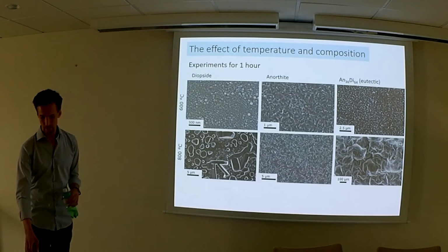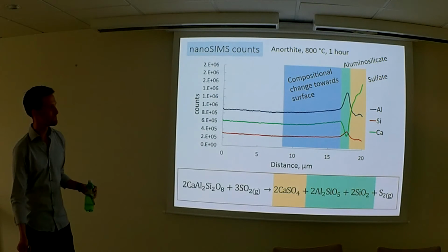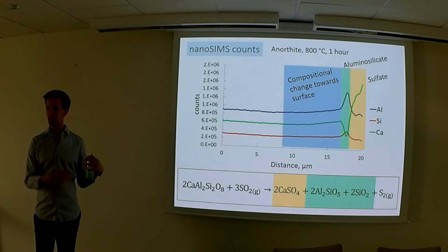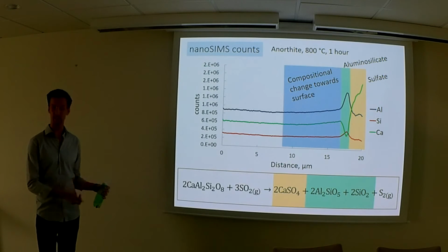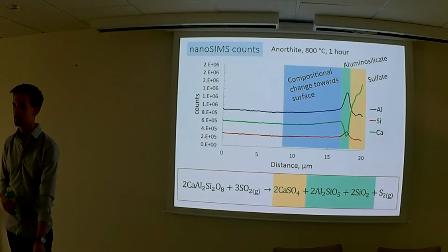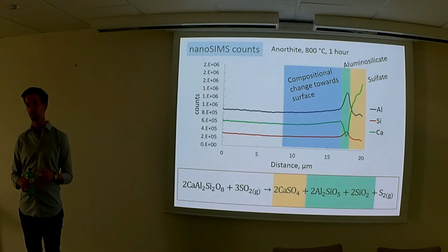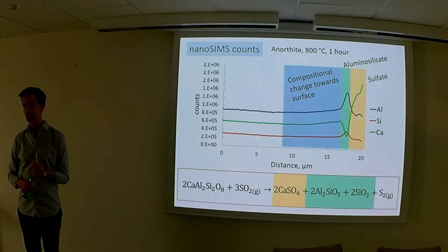Well, yes. That's why I went on the nano-SIMS. From those data, the idea is to try to obtain such diffusional data. Because even with reaction rate limited growth, you can have this kind of zone boundary. Right. Did you try to plot it against the square root of t, or something like that? No, I haven't. That may be the simplest way to show the diffusion controlled systematics.